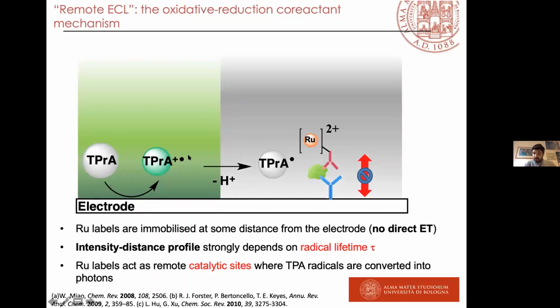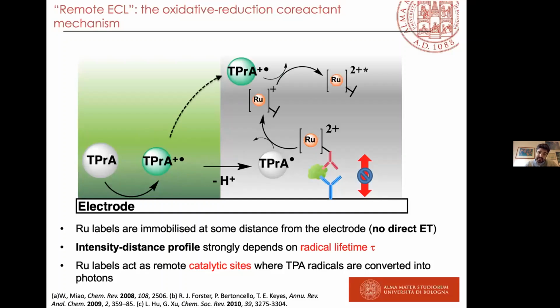This, of course, strongly depends on the lifetime of the radical cation, and you have a species that can reduce your ruthenium tris-bipyridine, and a species that can oxidize your ruthenium tris-bipyridine, and you can generate excited states. That's amazing, because with an easy and simple potential step, just applying the positive potential for the TPA oxidation, you can generate the emission.